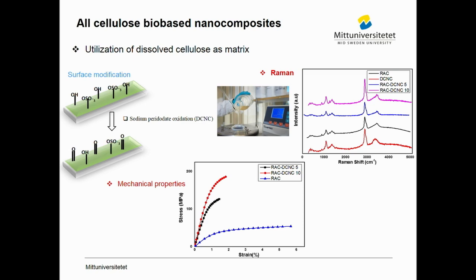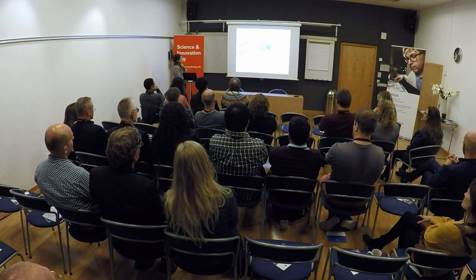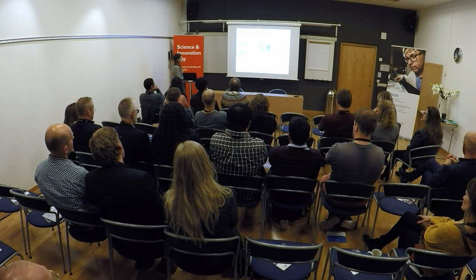Another focus of the group is using dissolved cellulose in alkali solvent. What we've been trying to do is reinforce this dissolved cellulose with CNC. Surface modification has been attempted first, then those modified CNC are added to the dissolved cellulose. The mechanical properties have been increased, and we can see that the crystallinity of the films has also increased after Raman characterization.